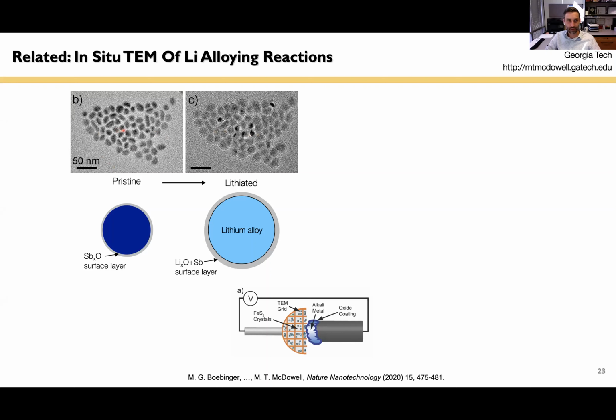What we find is when we lithiate these particles, by the way, I run through this part kind of quickly, so I apologize. There's a lot of details associated with how we do these experiments. If you're interested, we can talk after the presentation perhaps. But for now, I guess you'll just have to trust me that we do them well. I hope you will. But anyway, we have these little crystals and we're able to lithiate them inside the TEM, which is pretty cool. And when we do this, we see this process here. There's an expansion process. These are now lithiated nanocrystals.